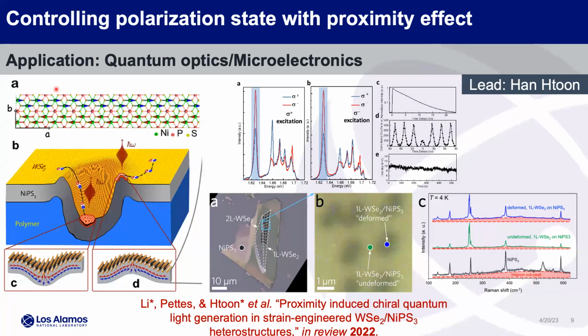And so Han Htoon led the DR. Our DRs are our big, like $5 million projects at Los Alamos. He led the last iteration of the DRs, and his DR was based on proximity effects. So proximity effects are, take this 2D material and put it on a magnet, a thin magnet. The reason you do that is because you can have effective fields in your material above 200 Tesla. It can be very, very high. So you're going to split the bands.